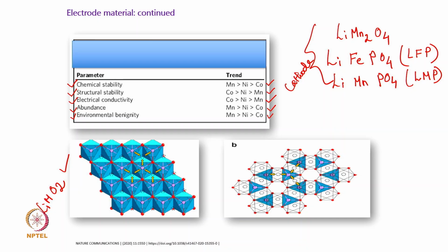In 3-dimensional spinel oxide it is just opposite: lithium moves from one tetrahedral site to another tetrahedral site through a vacant octahedral site. So, one needs to know two important things: the intercalation probability inside the cathode as well as the anode, and how lithium gets transported through the material.